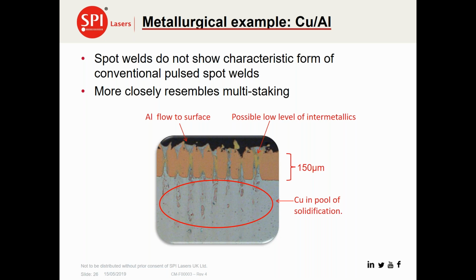This picture is an example of a 0.8 millimeter diameter spot weld, which can be achieved through 150 microns of copper onto 400 microns of aluminium in this case. And it's done in under 300 milliseconds. The process time is quite quick. It's done using a 70 watt EP-Z laser from SPI.